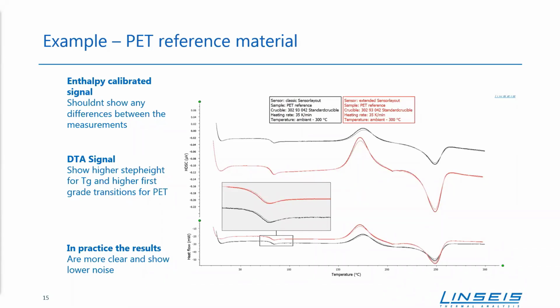But now we use a DSC because we want to evaluate enthalpies. So now let's plot the enthalpy calibrated signal. You can see there at the bottom. And yeah, there the difference between the two measurements isn't that big, as you can see there. Yeah, and if we have a look on the glass transition there with the zoom label, with the insert view, the step height of the glass transition is basically the same. And of course, this is also logical because we use almost the same sample amount here, and the material is the same. So also the measurement curve should be the same.